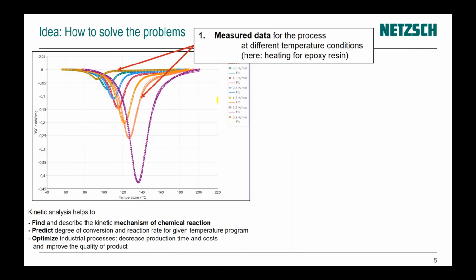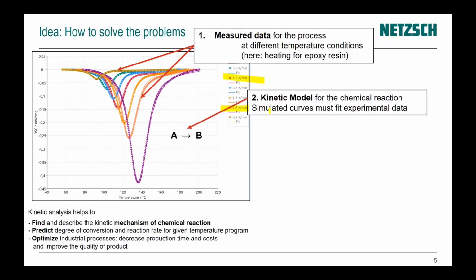How it works: firstly, we take our material to the laboratory and measure the same process under different temperature conditions, at different heating rates. You see here different curves because they're measured at different heating rates. After that, we create a kinetic model, because the curves differ due to temperature. But what stays the same? The chemistry is the same.